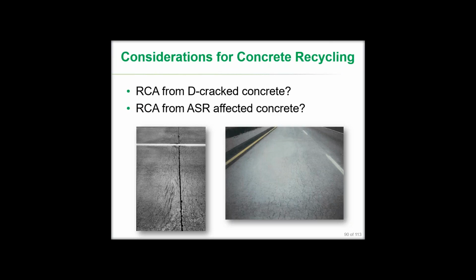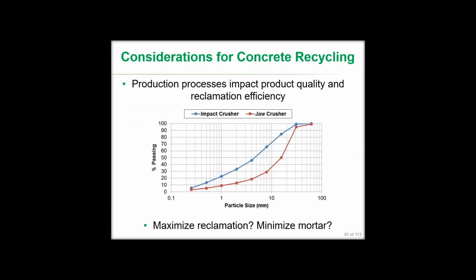Alkali silica reactivity was recycled on a number of projects, but again on an interstate pavement, Interstate 80, out near Pine Bluffs, Wyoming, near the Nebraska border. And as long as appropriate steps are taken to downsize the aggregate size on the D-cracking, basically do what you can to keep the concrete dry, prevent it from becoming critically saturated. And on the ASR side, doing the typical things that we do to mitigate for ASR with the use of Class F fly ash or lithium or other types of treatments, granulated ground blast furnace slag, and perhaps blending to reduce the amount of recycled material that's used. In both cases, eliminating fines in particular. So there's more details on that in both the sustainability handbook there, as well as in the references that are provided that accompany that.